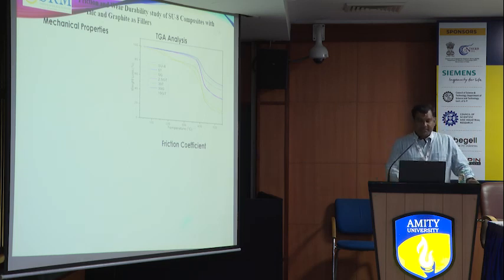That we achieve. And also you can see here the thermal analysis. This green line is pure SU8. It can degrade at approximately 330. So this is the degradation point. But when we add the filler, at least 100 or 120 degrees centigrade, we have improved the thermal stability. We can improve the polymer thermal stability up to 450. That was also a good achievement in that work.